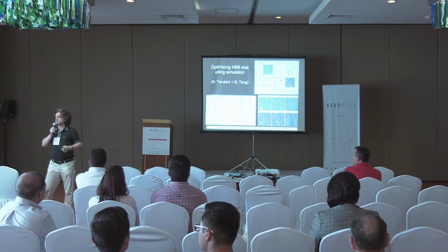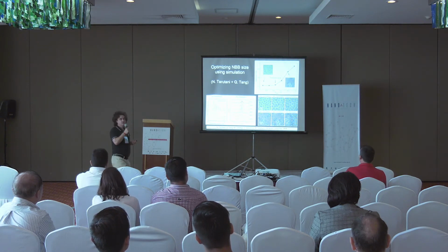And what we saw in the case, for example, of nickel hydroxide, is that when we use nano building blocks that were smaller than, say, 4 nanometers, the theory would predict, with all the optimized potentials, that we have a very good organization. These are patterns of organization obtained by theory. These are Fourier transforms. This is what we obtained from experiments. And for larger nanoparticles, the system will not give an order pattern.